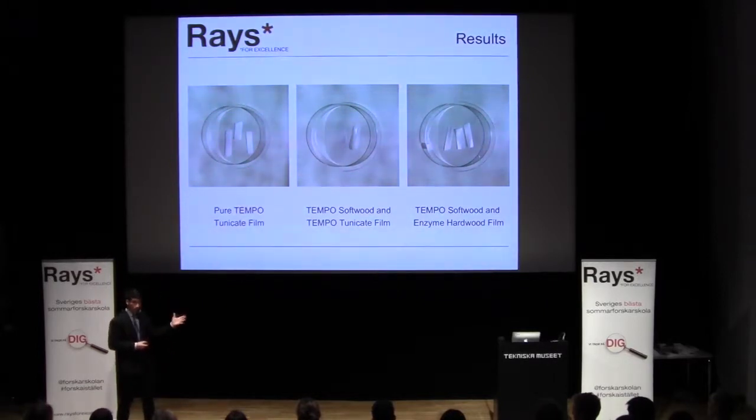On the other hand, hardwood made films much more brittle, rougher, and they crackle during testing, which is definitely not something we want. Now, this might be due to the difference in material or their pre-treatment processes, but further investigation and research needs to be conducted before any conclusions can be made.